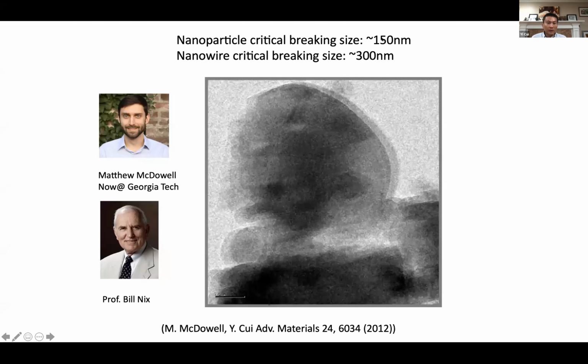The critical breaking size is roughly about 150 nanometers for the particles. The wires is about 300. This detailed reason of why wires is slightly bigger is stress accumulation across different dimensions that could explain that. The size identified using this method is important. That can guide us with the material design, how small we want the particles to be in order to avoid the breaking.